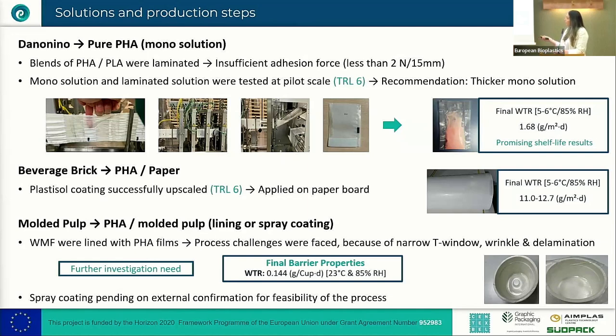Also, we worked with lining solutions, where you can see here, we lined some cups with monofilm of PHA. I have to be clear about this: working with PHA is not easy, but the know-how is there, and we worked really hard to manage to line these cups. And as you can see, the final barrier properties are promising. We still have some small issues to overcome, like the narrow temperature window, some wrinkles, and so on, but we think that those are the foundation stones to go for an actually market-ready solution here.